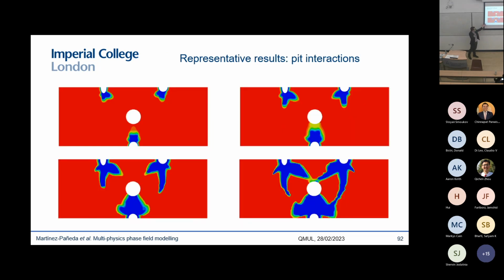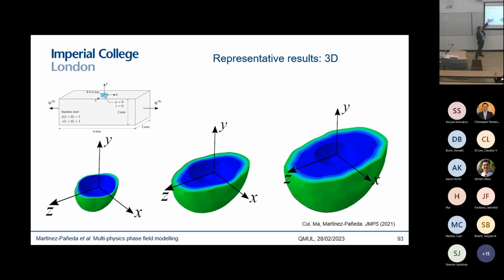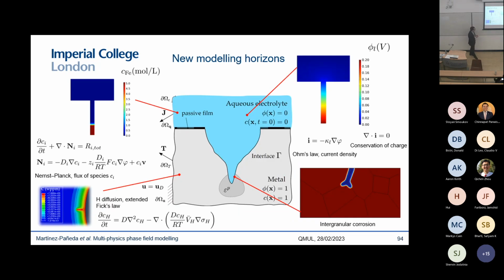And just to show you that, of course, if we're using phase field, we can capture very complex pitting conditions, and we can do this in 2D, we can do this in 3D. And I'm quite excited about this area. I think that we're going to see a revolution in corrosion modeling, similar to what we have seen in microstructural evolution or fracture, because people will typically tell you that corrosion is very difficult to model with computers. They would say that it is too complicated a process, there are too many things happening at the same time, in addition to this situation where you need to accurately track this cracking morphology or this corrosion morphology. But the thing is that we know we have equations that describe each of those physical phenomena, and now we have a tool finally that allows us to couple all of those and to track the corrosion.